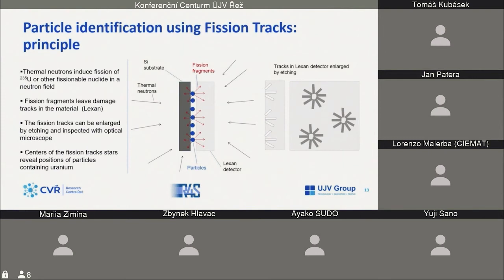Then the second method which we use for particle identification is the fission tracks. Here I would like to briefly explain the principle of the method. Here the particles on a substrate are inserted into a neutron field. Thermal neutrons are coming from all directions and induce fission of uranium-235 in particles where it is present. And fission fragments emitted from those particles leave damaged tracks inside material around them.